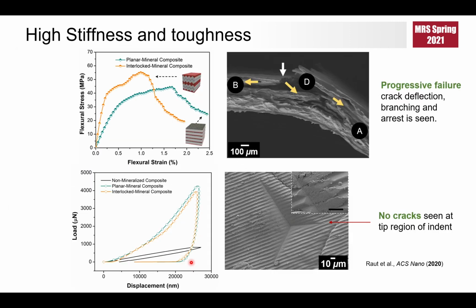Moreover, we observed progressive failure in the nacre mimetic composite. In 3-point bending experiments, the work of fracture of the interlocked composite is found to be 36% higher than that of the control sample. Also, inspection of the fractured composite shows that cracks deflect, branch, and eventually arrest within the composite, indicating a progressive failure and not a catastrophic failure.